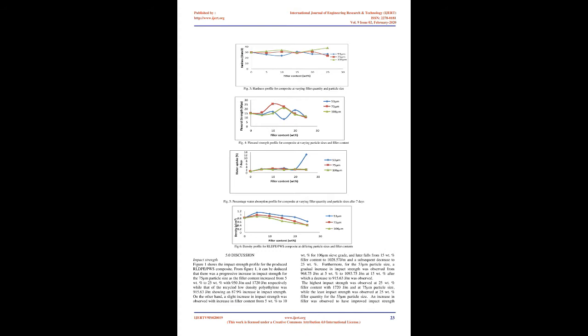Addition. Tensile strength. Figure 2 shows the tensile strength of the composite material produced. The profile shows a progressive decrease as filler quantity increased from 5 weight% to 25 weight% for 106 µm, with 9.50 MPa and 3.33 MPa respectively. For the 75 µm particle size, there was an increase in tensile strength as the filler quantity increased from 5 Wt% to 15 Wt%, with values of 7.40 MPa at 5 weight% and 7.89 MPa at 15 weight%, beyond which there was a decrease in tensile strength to 3.57 MPa at 20 weight% filler content, and 3.55 MPa at 25 weight% filler content.